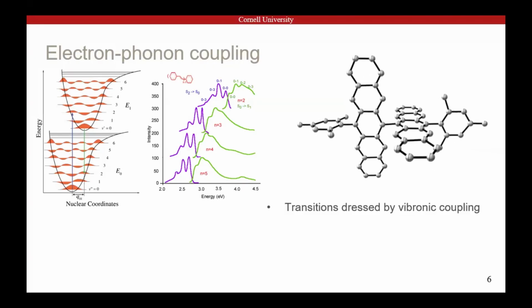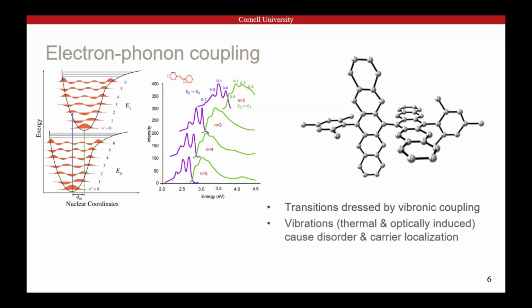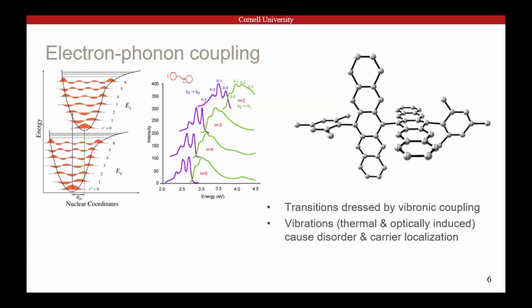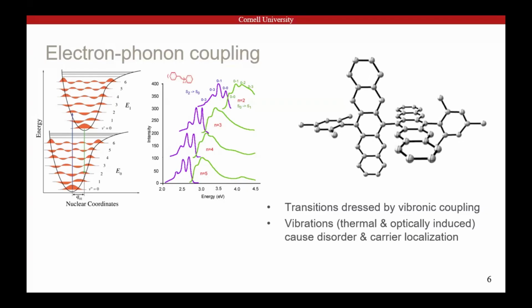Simple enough. And this does well to describe most of the basic steady-state spectra of organic materials, but it doesn't tell the whole story. Among other things, these vibrations, which are very soft and easy to activate, are one of the main culprits that causes this carrier localization, the exciton localization on the previous slide. So they're deeply tied to this transport problem. They cause a lot of the broadening and disorder that we can't get away from. So they come with an important cost, but they also have a crucial advantage.